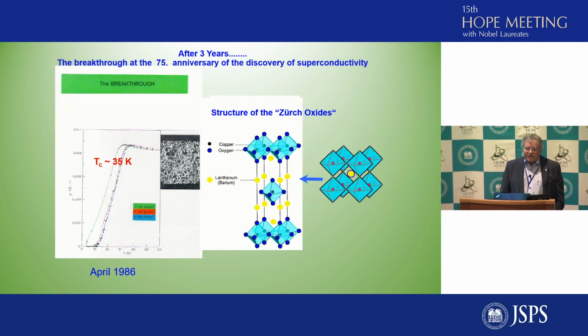So, after 3 years, at this 75th anniversary of the discovery of superconductivity by Kamerlingh Onnes, we came up with a new record temperature in a completely new material. So this was a raise in transition temperature from 23 Kelvin, which was the maximum in the intermetallic compounds, to 35 Kelvin, which is really the transition temperature.